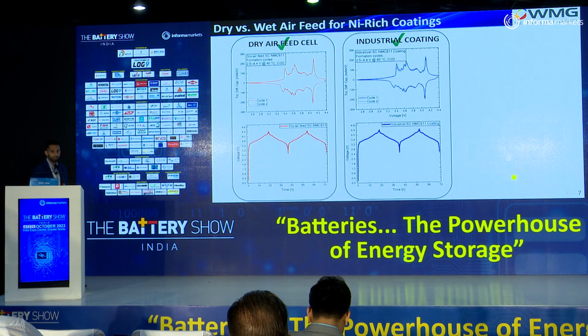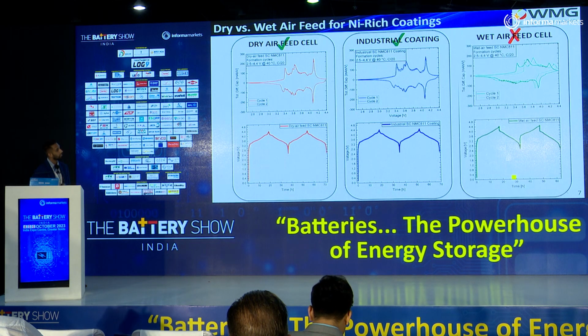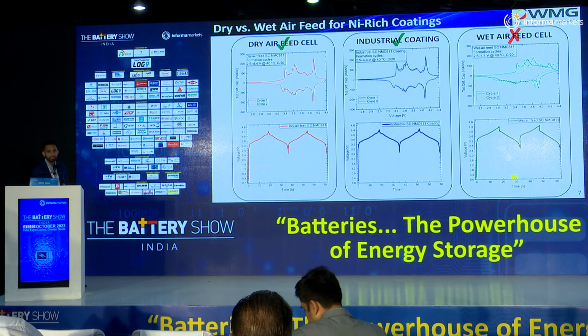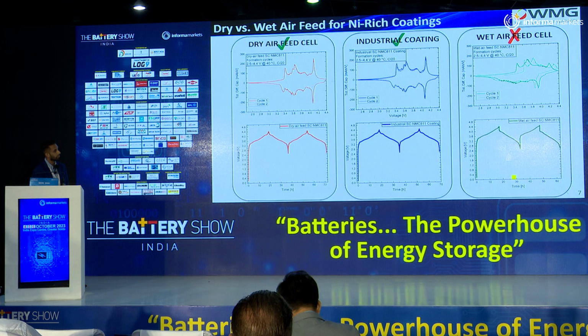Comparing this to a wet coating, and why do we need good humidity control in our pilot line? Well, you can see here that the first two cycles don't even align. They're also shorter in terms of area, indicating a lower capacity. So the humid air feed, which we've also coated in our pilot line whilst turning off the dry air feed, indicates that we require good humidity control to produce high-level, high-quality cells.